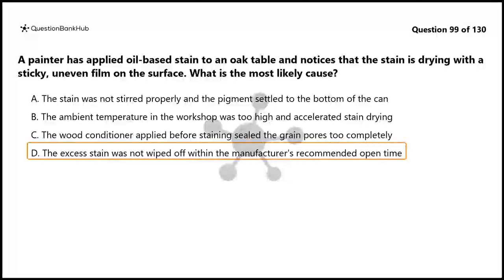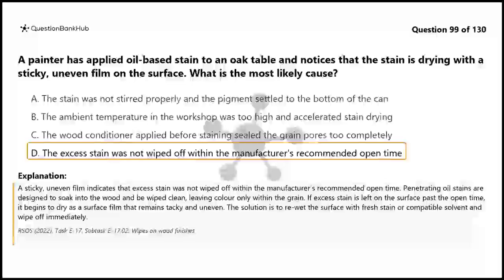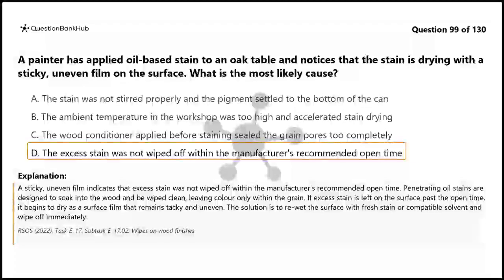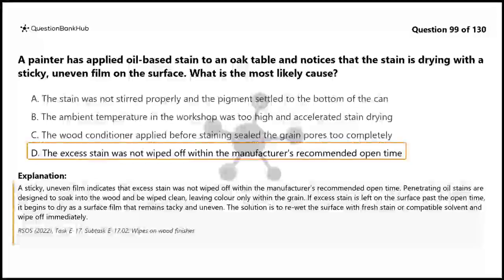The correct answer is D. A sticky, uneven film indicates that excess stain was not wiped off within the manufacturer's recommended open time. Penetrating oil stains are designed to soak into the wood and be wiped clean, leaving color only within the grain. If excess stain is left on the surface past the open time, it begins to dry as a surface film that remains tacky and uneven. The solution is to re-wet the surface with fresh stain or compatible solvent and wipe off immediately.